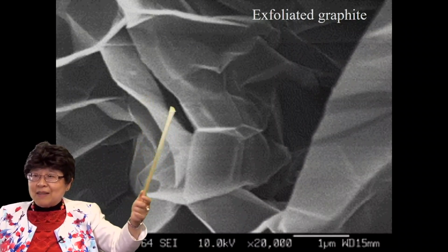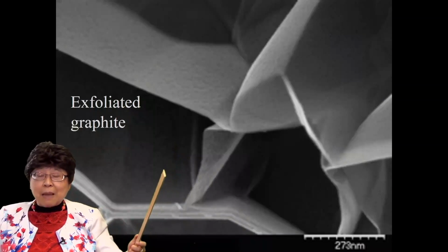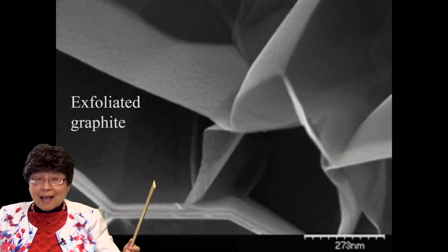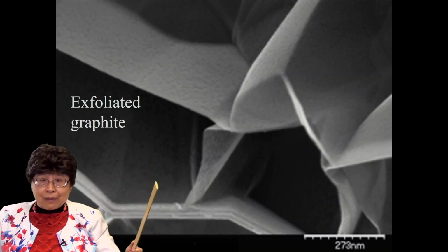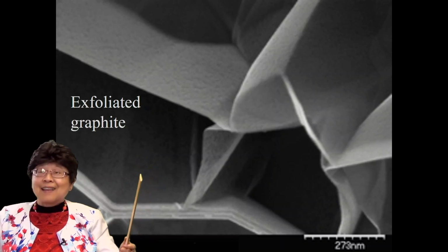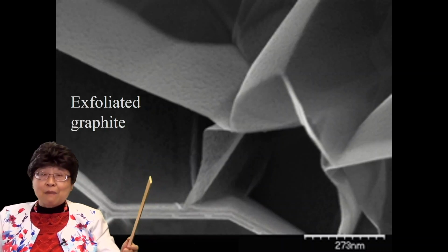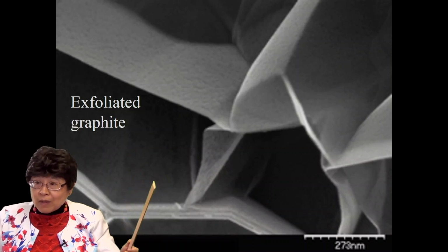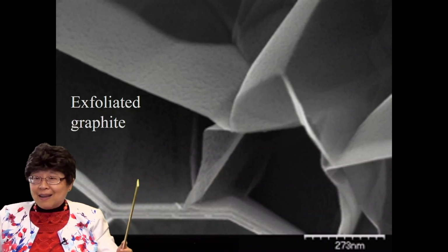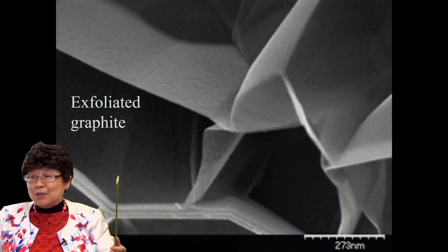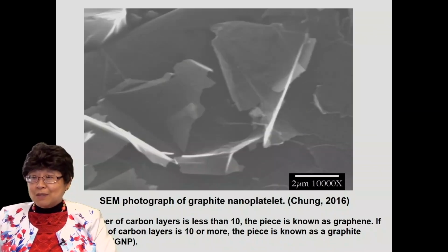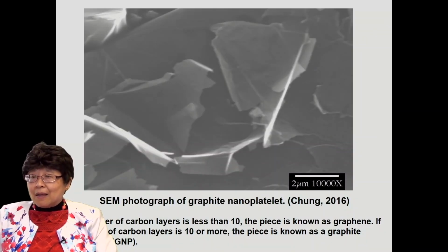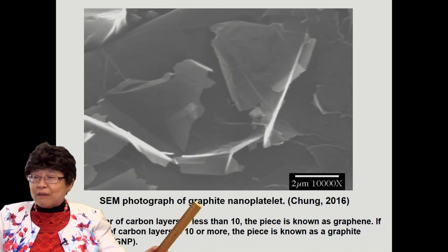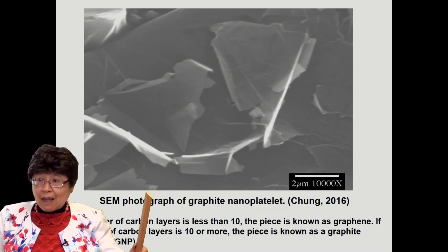And you see the carbon layers very separated. Okay? In fact, this is the mother of graphene. This is one way of making graphene: making exfoliated graphite and then shaking it to make it loose and form graphene. And this is what's called graphite nanoplatelet, which is formed by exfoliation and the shaking.